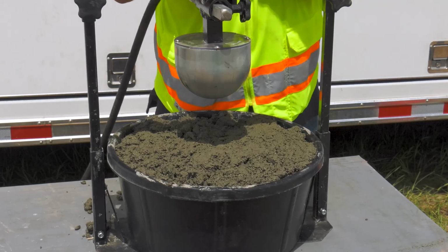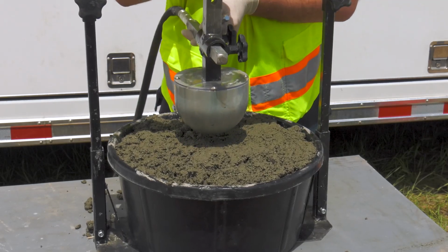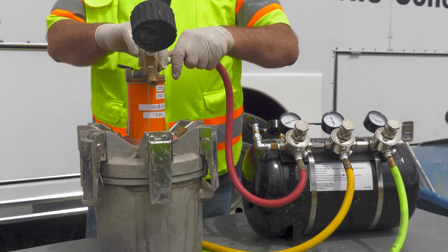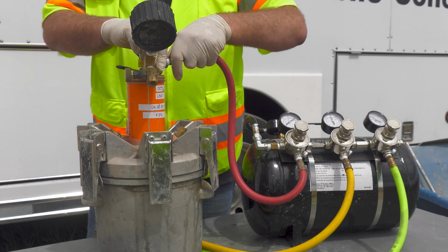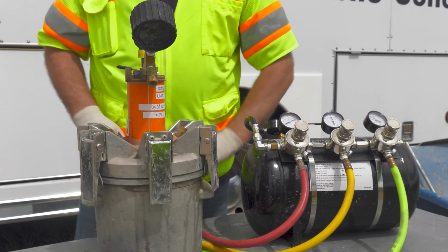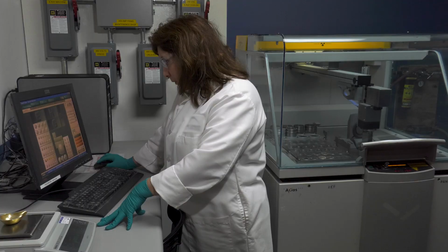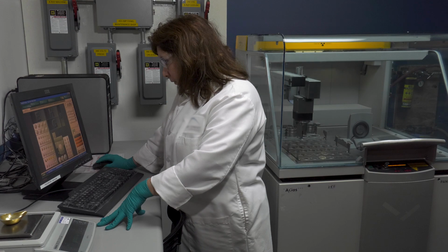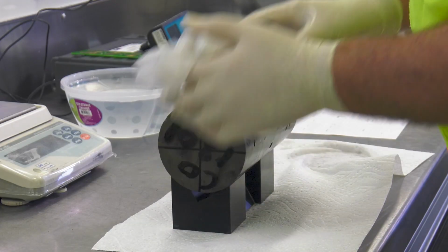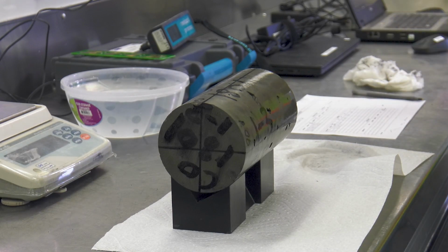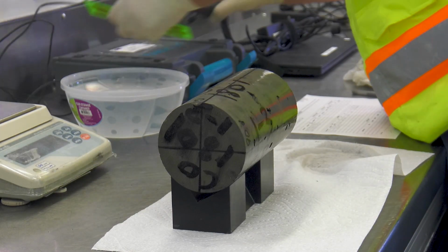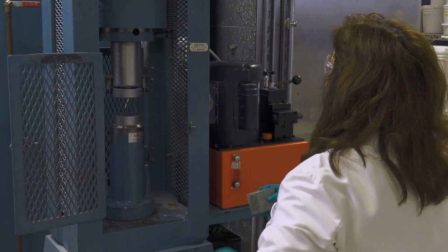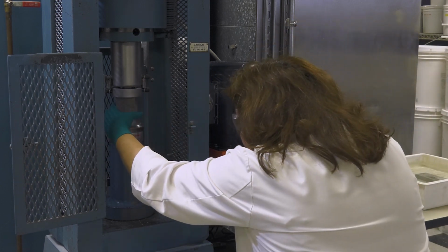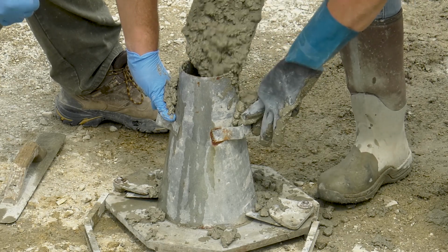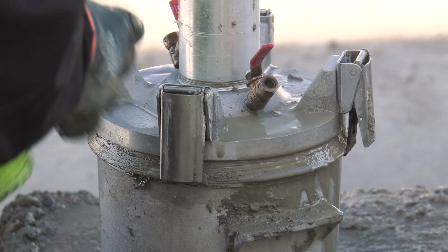A number of tests that meet these criteria are included in AASHTO PP 84, which is a guide specification that includes tests completed either during mixture design or at placement or both. The tests included in PP 84 relate to durability characteristics of the concrete mixtures, and the tests are flexible enough to allow highway agencies to pick and choose the tests that are most suitable for them. Moving forward with this approach encourages agencies to measure the properties that relate to durability rather than relying on slump, strength, and total air to assess their concrete.